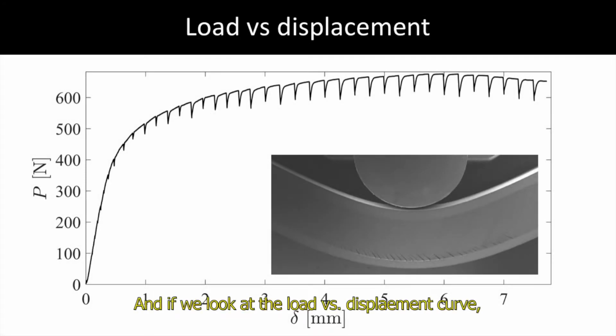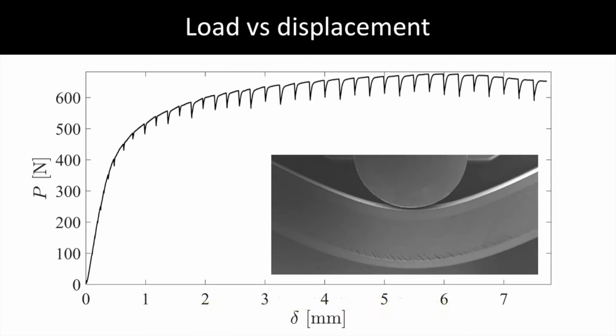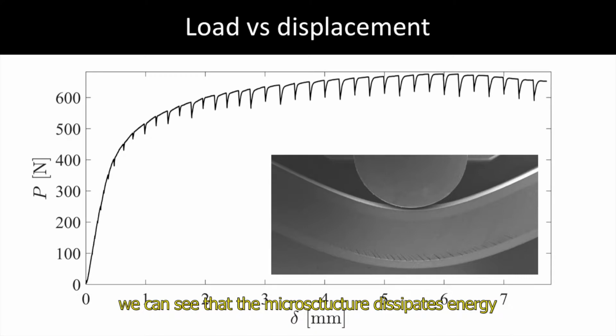And if we look at the load displacement curve, all the load drops are caused by specimen relaxation while we pause the test to take images. We can see that the microstructure dissipates energy in a very stable manner under more or less constant load. The microstructure can be loaded up to large curvatures without it losing its load carrying capacity.